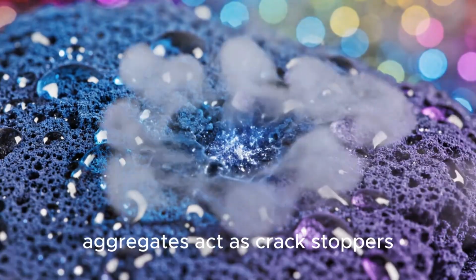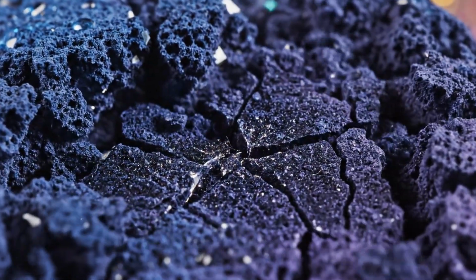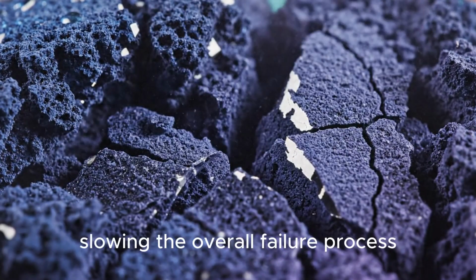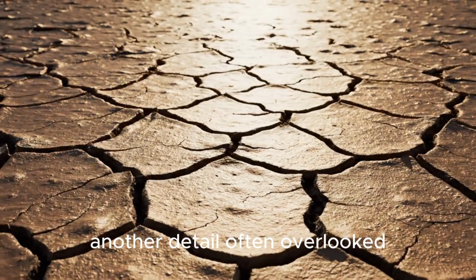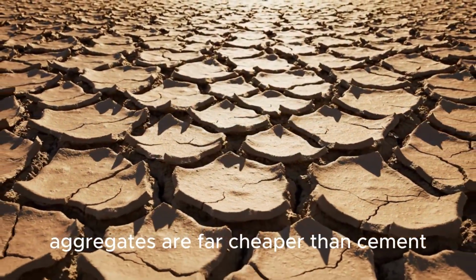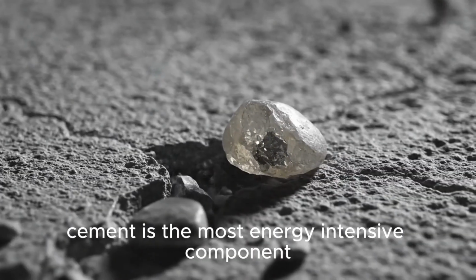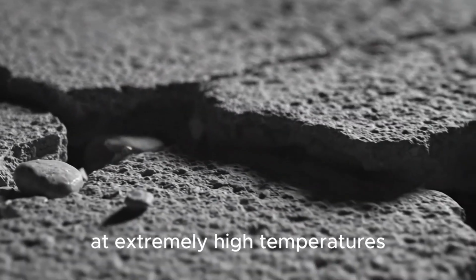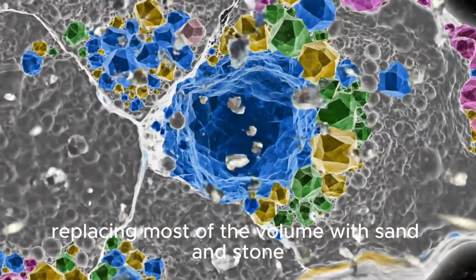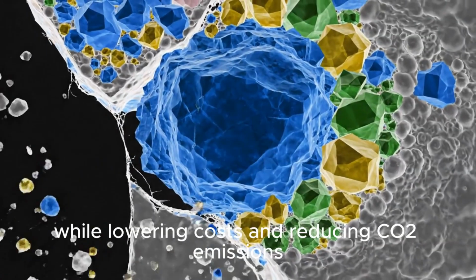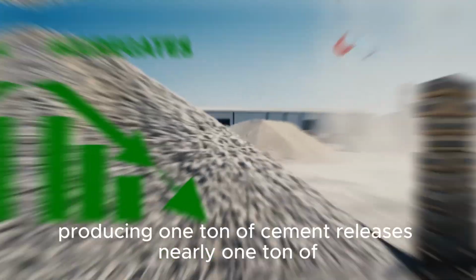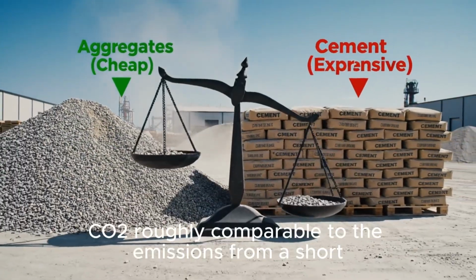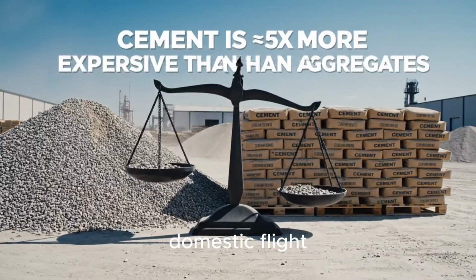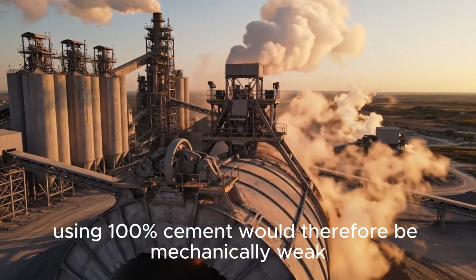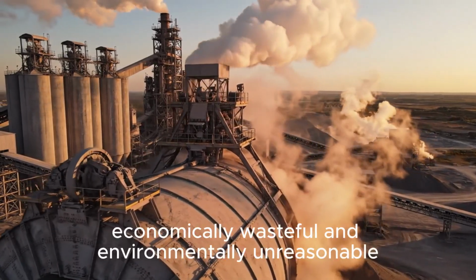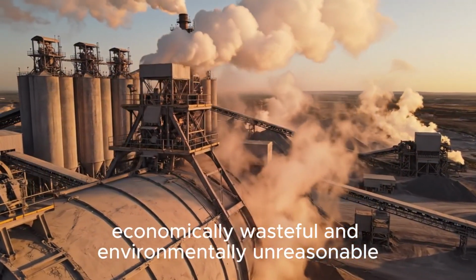Aggregates act as crack stoppers. When a crack reaches a piece of gravel, it deflects or stops, slowing the overall failure process. Another detail often overlooked: aggregates are far cheaper than cement. Cement is the most energy-intensive component in concrete because it must be produced at extremely high temperatures. Replacing most of the volume with sand and stone improves mechanical performance while lowering costs and reducing CO2 emissions. Producing 1 ton of cement releases nearly 1 ton of CO2, roughly comparable to the emissions from a short domestic flight. Using 100% cement would therefore be mechanically weak, economically wasteful, and environmentally unreasonable.